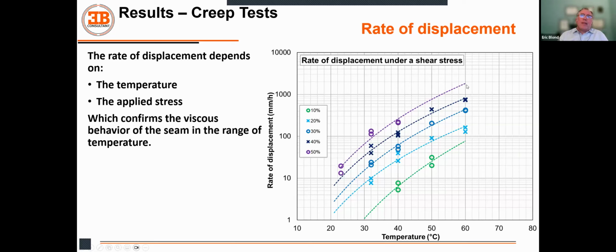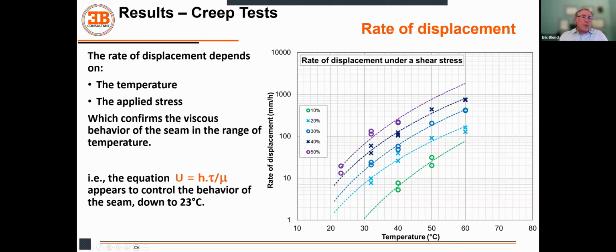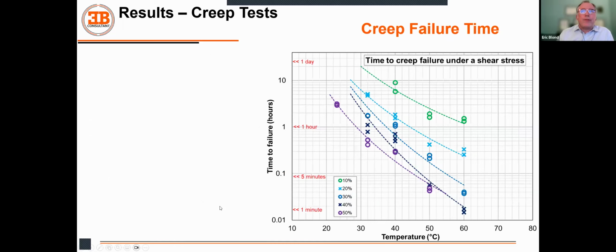And we confirm that, again, there is this relation connecting together the speed of displacement, rate of displacement, so the U value in my viscosity equation, with the temperature for a variety of stress. So this really confirms that these equations do control the behavior of the seam.